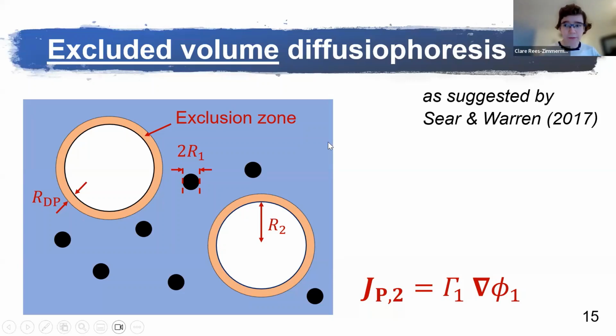So excluded volume diffusiophoresis is relevant in mixtures of particle sizes, where the small particles are excluded from a certain distance around the edge of each of the large particles. You can imagine having a tennis ball and a football, and you cannot physically get the center of the tennis ball past one tennis ball radius away from the edge of the football, simply because they would overlap. And this is what this effect is.